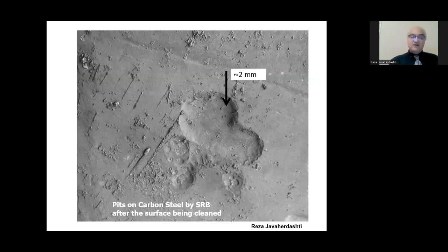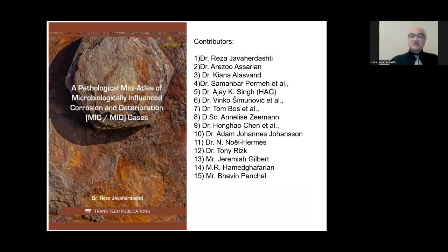This is an example of carbon steel. I think the overall thickness was about 2.5 millimeter or so. It was less than 3 millimeter for sure. And we got these features of pitting with a depth of 2 millimeter caused by sulfate-reducing bacteria. Then this is the book that I mentioned earlier, a pathological mini atlas of microbiologically influenced corrosion and deterioration. And I am honored that I had 15 contributors for case histories from around the world, different countries, different industries. I will share with you a few of them.